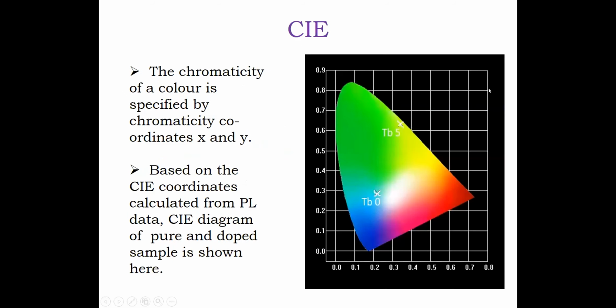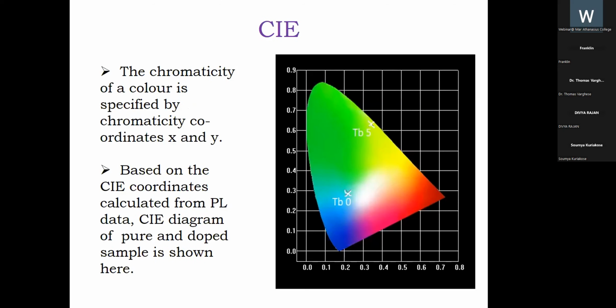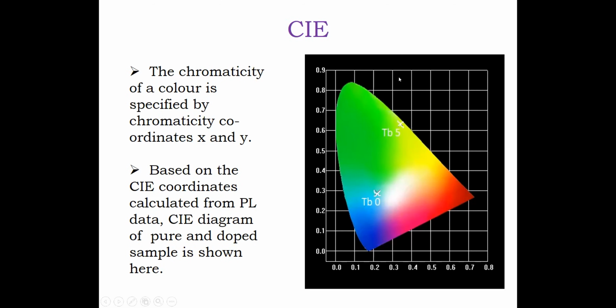Next, ma'am. CIE chromaticity diagram. CIE is a standard color matching reference which helps numerically to identify a color. Chromaticity of a color is specified by the chromaticity coordinates X and Y, which are calculated from PL data. And the calculated chromaticity coordinates are shown in the table and are pictorially indicated in the CIE diagram. The terbium 0 sample shows a greenish blue emission, and the terbium 5 shows a yellowish green emission. Due to the incorporation of terbium ions into the lattice, the color of emission changed from blue to green region.